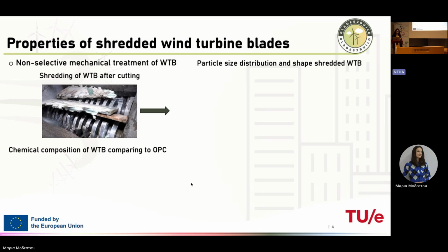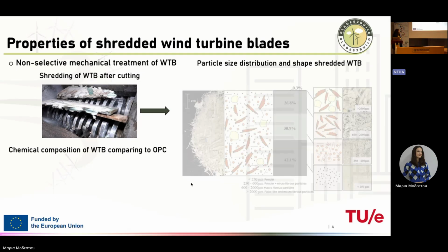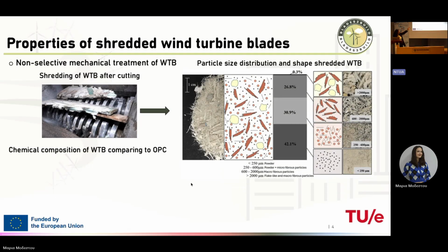Here is the process of shredding the wind turbine blade. They preliminarily cut it into pieces, then shredded it. And here is a visualization of what we see in optical microscopy analysis. We have powder, actually 40 to 45% is powder. Then we have a kind of fibers, and a kind of flakes, which are really flat particles, which, spoiler, are not really efficient. The least efficient part of this waste is these flakes.